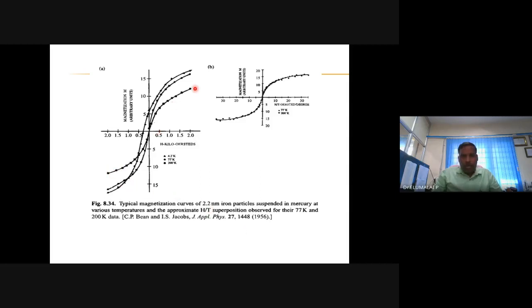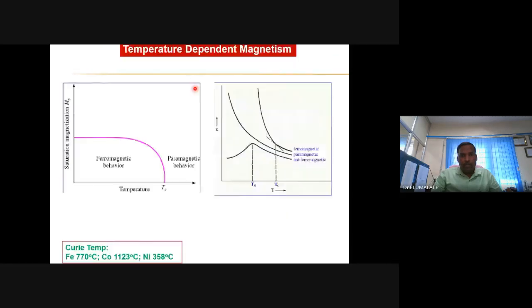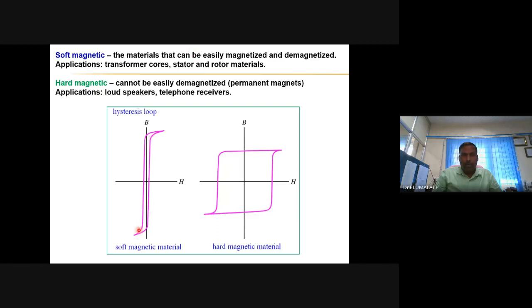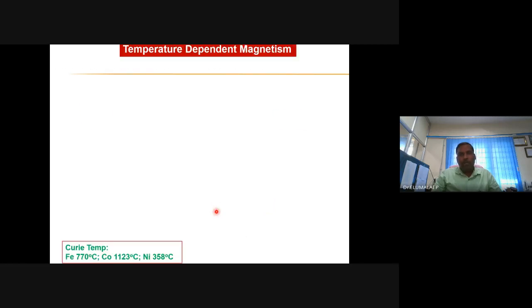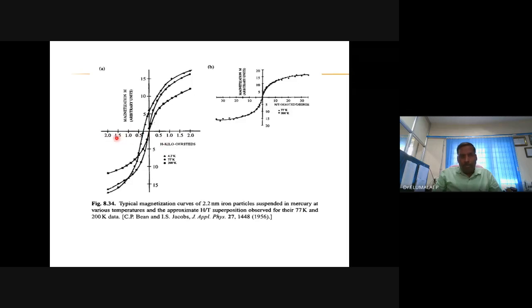No hysteresis. Unlike in the bulk material, there is hysteresis. Bulk materials, depending on the soft magnet or hard magnet, have a hysteresis. But in the case of superparamagnetic materials, there is no hysteresis. You take a ferromagnetic material, make it into a nanoparticle, then place it in a magnetic flux and increase the magnetic field, then you remove the magnetic field, it will follow the same path. No hysteresis. This is the characteristic of superparamagnetic materials.